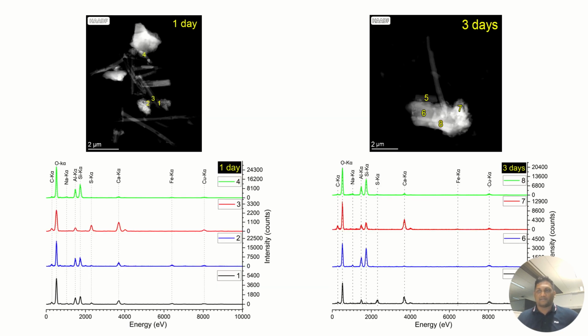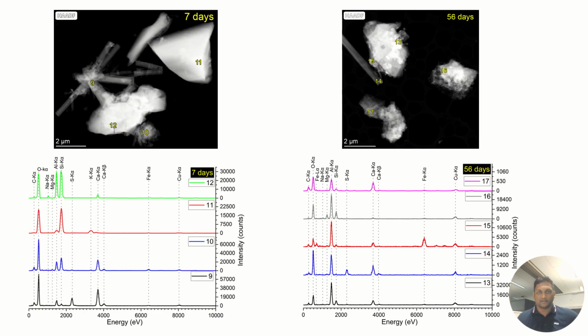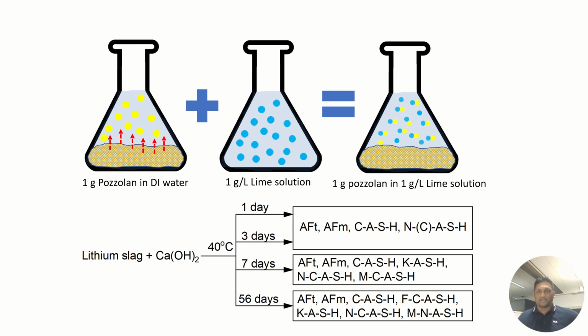The crystalline and amorphous intermediate hydration products were analyzed in SEM-EDS. The peaks were analyzed at 1, 3, 7 and 56 days for the same XRD samples. The peaks are analyzed and the probable hydration products are summarized here. At 1 and 3 days, ettringite, secondary ettringite, and sodium and aluminum based calcium silicate hydrate was formed. This indicated the premature hydrated gel initially expands and forms gel and capillary pores.